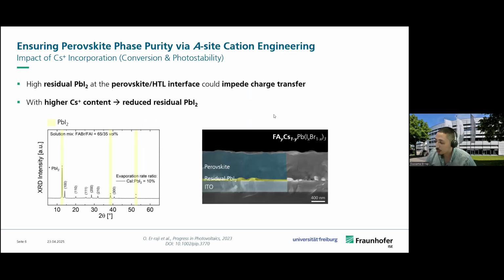So one of the important things that we always have to ensure when making perovskites with the hybrid method is to have a good balance between the inorganic precursors in the first step and the organic precursors in the second step to have a stoichiometric perovskite film. And one of the issues that we often see is that we don't have a phase pure perovskite.